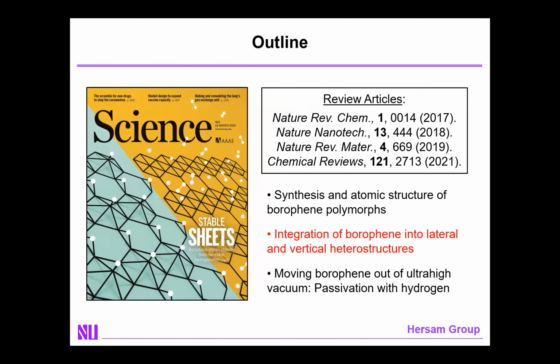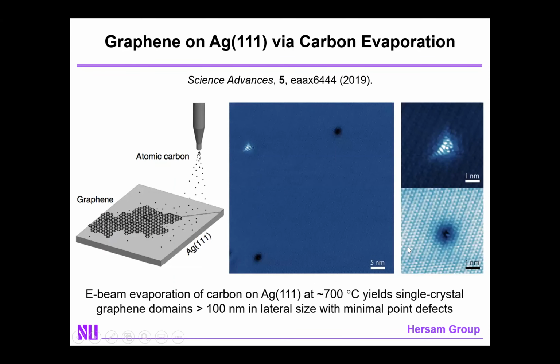Okay, so let me move on and talk about how we can now take these borophene materials and integrate them into more complicated lateral and vertical heterostructures. The first one we went after was a borophene graphene heterostructure, and our strategy was to realize that on the same silver 111 substrate that we grow borophene, you can also grow graphene. And you do it in a very similar way by, in this case, evaporating atomic carbon onto silver 111 at